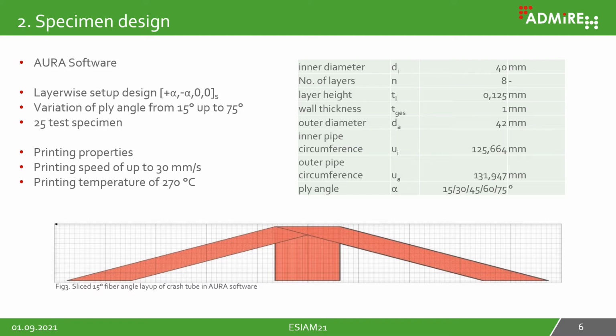To design our specimen, we used the Aura software from Anisoprint. We created a layer-wise setup design of an alternating ply angle and 0-degree plies in between. It's a symmetrical stack in itself. We variated the ply angle from 15 up to 75 degrees and printed 25 test specimens in total.